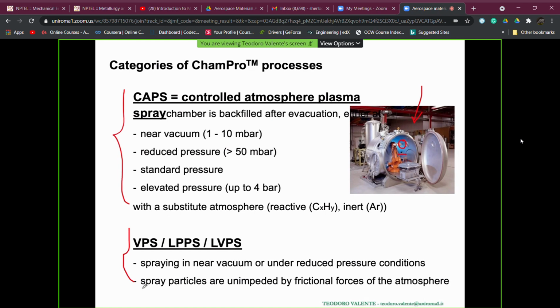And in this case, as we have said before, we are going to reduce the frictional force of the atmosphere because we are going to a lower value of pressure, so the plasma plume will be longer. And this means also that we can have higher residence times of the particles inside the plume, and we need higher spray distance.